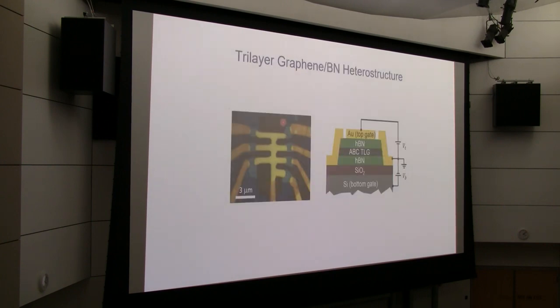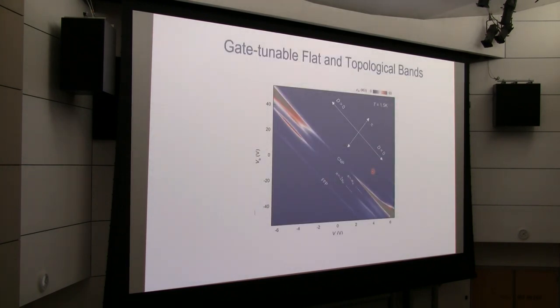So we went to make this type of sample with ABC trilayer graphene aligned with boron nitride. And we also make a so-called dual gate device where we have both a top gate and a bottom gate. So in that case, we have two controls that will allow us to control the electrical field and the carrier doping independently. So here we show the overall phase diagram where you measure resistance as a function of top and bottom gate. If you look at the 45-degree direction, you are changing the carrier density without changing the electric field. And if you look at the 135 direction, you are changing the effective field with fixed carrier density.